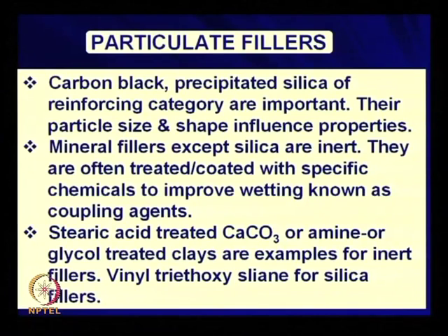So it will make a coupling between silica filler and the polymer. Here also stearic acid, being organic in nature, has one carboxyl group, the polar side, that will be oriented towards the calcium carbonate side, and the organic chain will remain on the other side, which will mix with the polymer. So this is the basic principle. Okay.